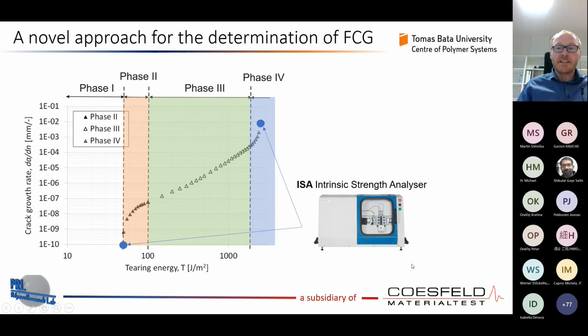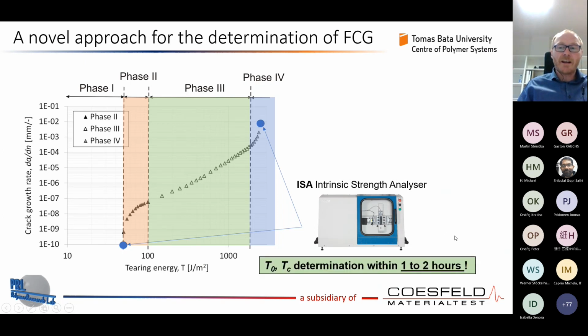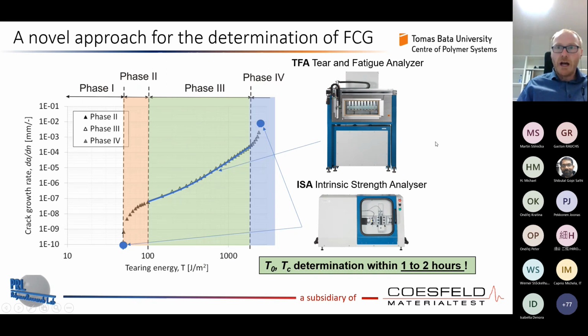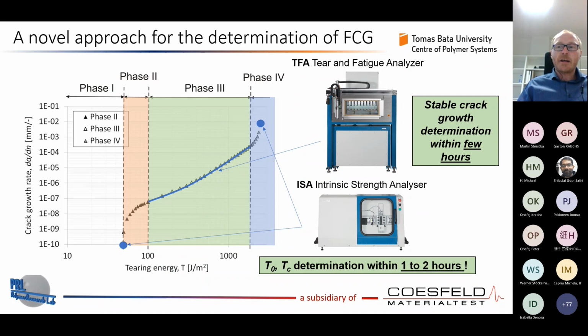So how to proceed more efficiently to determine complex fatigue crack growth behavior in minimal time with highest accuracy? There is a possibility, as Chris introduced. These 2 points, T0 and TC, can be determined very quickly, within 1 to 2 hours, with that intrinsic strength analyzer. So we would have these 2 points. For the middle part, there is a very okay time to analyze it, very efficiently and very accurately, with the Tear and Fatigue Analyzer. That's very common, and that is the best choice to do it. So this is a stable crack growth determination within a few hours. So generally, within a few hours, we can have T0, TC, and the stable crack growth. And of course, the question is how we could get these parts to have an exact, complete fatigue crack growth curve. This is what we would need to have.